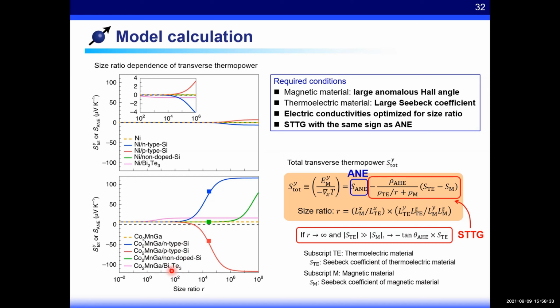But nowadays, the theory predicts that a large anomalous Hall effect does not necessarily result in a large ANE, right? Yes, exactly. But STTG is completely different from the anomalous Nernst effect. Here, the anomalous Hall effect is the driving force. So we should choose a magnetic material showing a large anomalous Hall effect, even if the material shows a very small Nernst effect. Okay, thanks very much for the clarification.